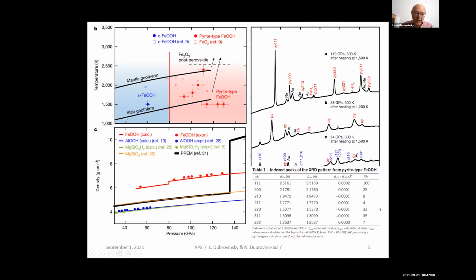But they also compare this with a slab geotherm. And if you look carefully, you see that this slab geotherm assumes that at a depth of around 2,500 kilometers, pressure around 120 GPa, the temperature hardly reaches 1500 K. I would say that this is really a qualitative approach, and I can reproduce it. If you take, like the authors did, the geotherm calculated up to 250 kilometers, and linearly extrapolate it to 2,500 kilometers, you really get these temperatures.